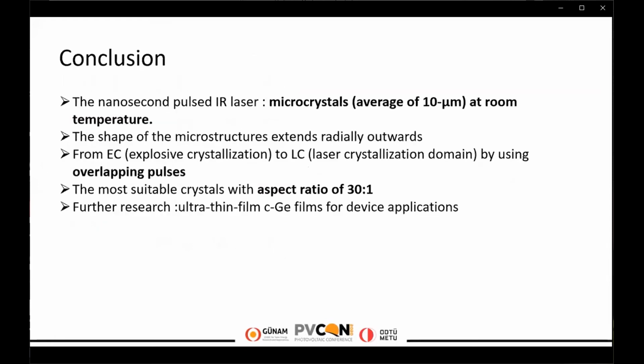As a conclusion, in this study, we achieved to process the germanium ultra-thin film in a controlled manner via nanosecond pulsed infrared laser. The nanosecond pulsed infrared laser creates microcrystals which have an average size of 10 micrometer on the 300 nanometer thick amorphous germanium on glass at room temperature. This study introduced micro polycrystalline germanium, demonstrates the laser crystallization of 300 nanometer thick amorphous germanium via nanosecond pulse infrared laser and provides new device application of photovoltaic technology and thin film transistors.